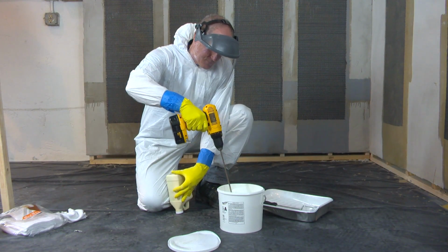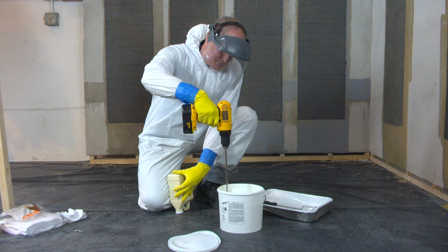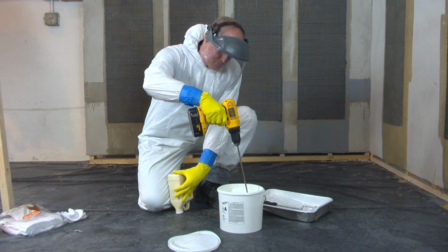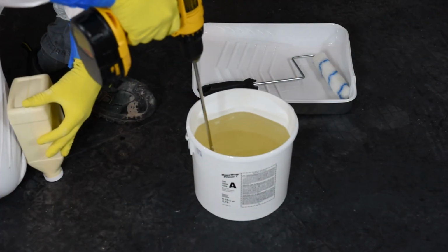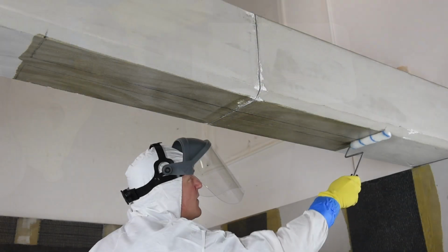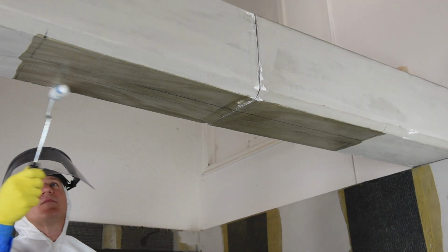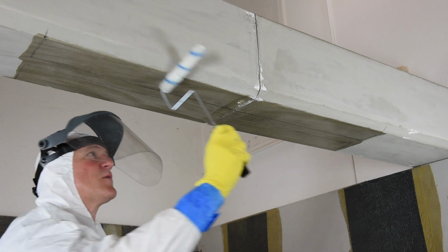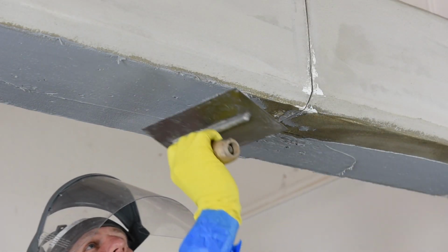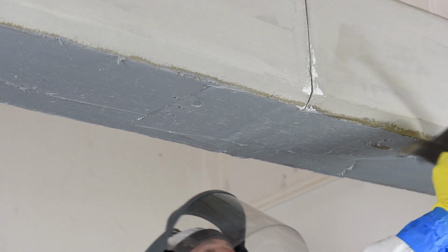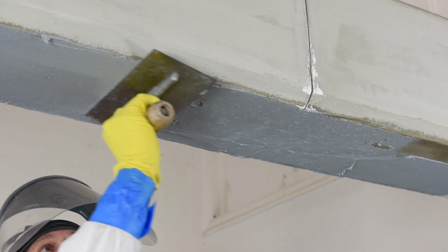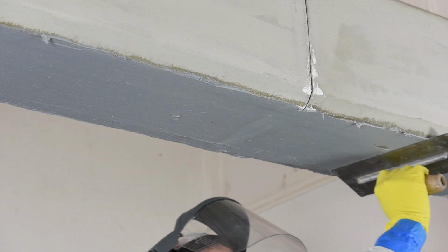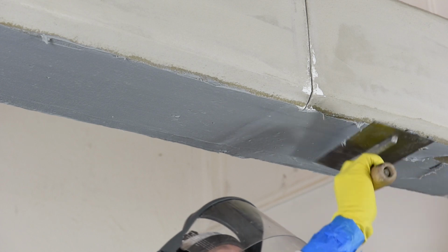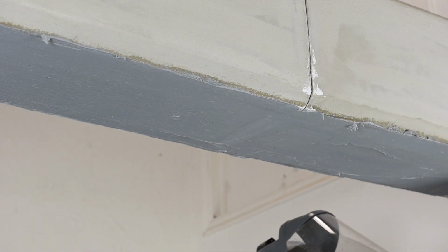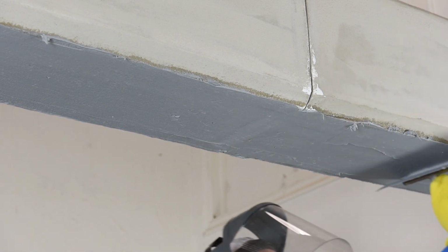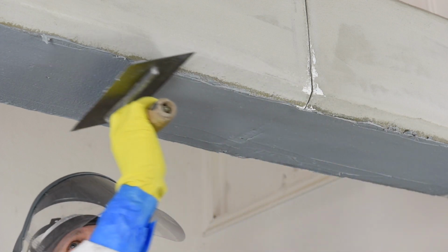As with the other carbon fiber products, MapeWrap Primer 1 is installed onto the substrate to consolidate and improve bonding of the Carbo plate products. The MapeWrap 11 or MapeWrap 12 serves as a leveling product as well as an adhesive for bonding the Carbo plate laminates to the substrate. Once the primer becomes tacky, MapeWrap 11 or MapeWrap 12 is installed onto the substrate at a thickness of 1/32 to 5/64 of an inch, or 1 to 2 millimeters.